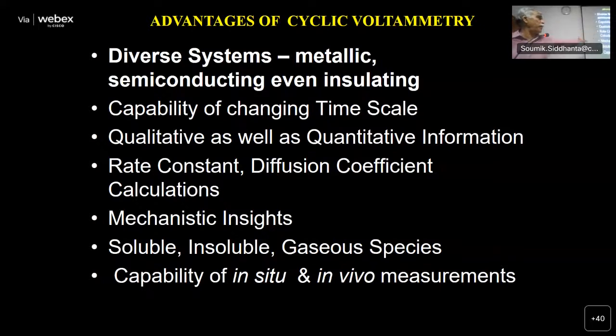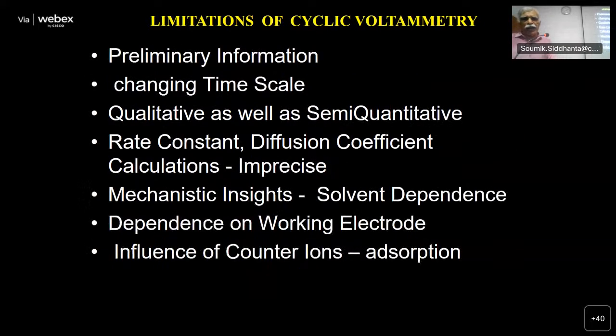Mechanistic insights can be obtained, EC, ECE, and the HOMO-LUMO gap can be estimated, assuming that solvation is not changing the electronic structure. For conducting polymers it is a routine thing that people use peaks and calculate what the HOMO-LUMO gap is. Soluble, insoluble, gaseous species you can do. NO can be bubbled in the electrochemical system, and you will be able to calculate using voltammetry. Capability of in situ and in vivo measurements, especially in biology, in vivo measurement is very important. And these days, it's also possible to have in operando techniques, like in batteries, while charging, discharging, you can acquire information by doing voltammetry. Limitations are there.